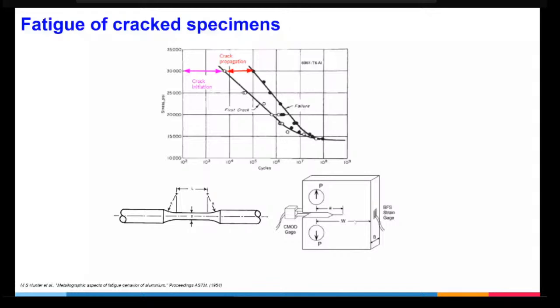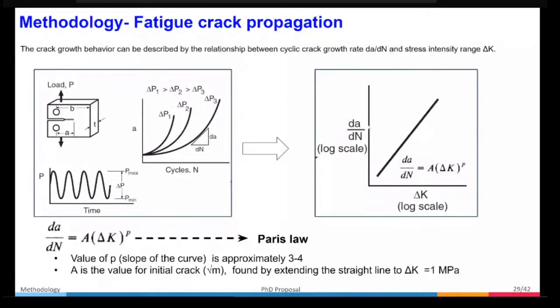Most of the tests are done using mode 1, called crack opening mode, and basically we record the crack propagation rate, da/dN, where a is the crack length, with respect to delta K. Here delta K is the stress intensity range. You can later fit this using the Paris law, da/dN equals A, which is a constant, times delta K to the power P. The P value generally ranges approximately from 3 to 4. Once you plot this curve and find da/dN is a straight line, you can use that and take these values to compare other materials.